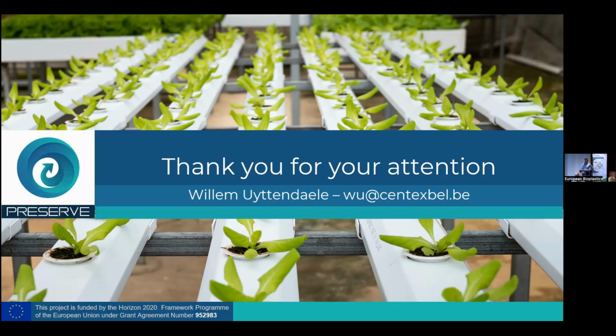There is a question online. Aman is asking, have you done an aging study on these coatings? And if yes, are they stable, especially in the presence of water and heat? He is assuming that coating is done at high temperature above melting point. Yes, the coating application is done at high temperature. To gel this PHA at the moment, we need about 170 degrees. But when it comes to the stability of the PHA, this is something we haven't tested in the packaging. But since we're a textile institute, we also investigated the use of PHA as artificial leather. And in that sense, we did some outdoor UV and weathering testing, simply on the roof. After a month, there was only minimal damage to this PHA artificial leather. So to some extent, the PHA coating is quite stable.